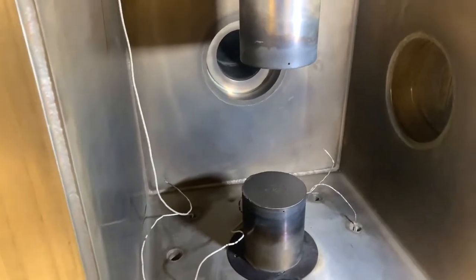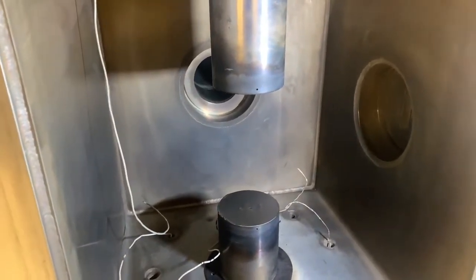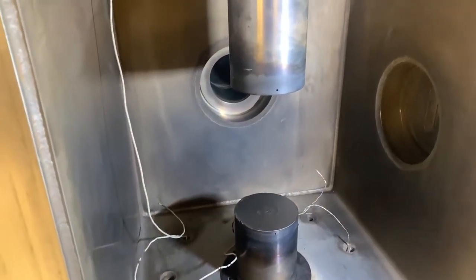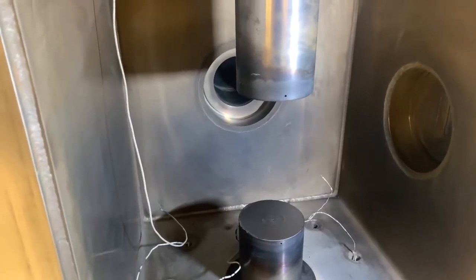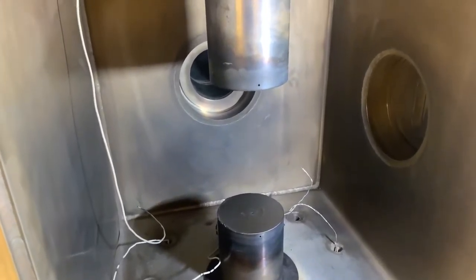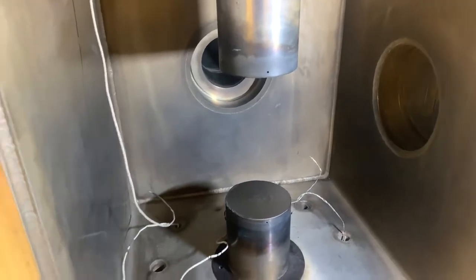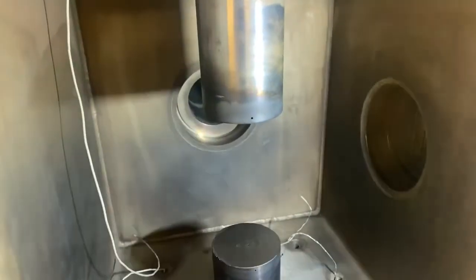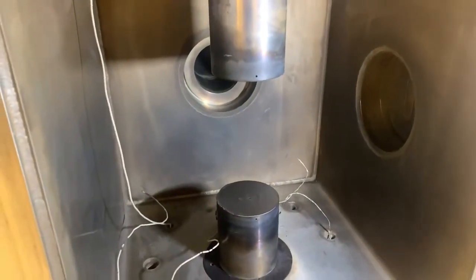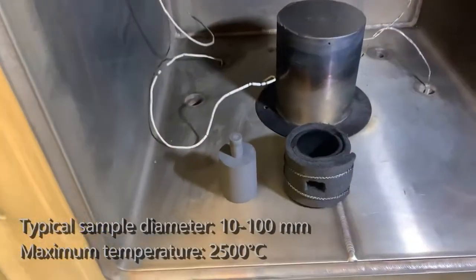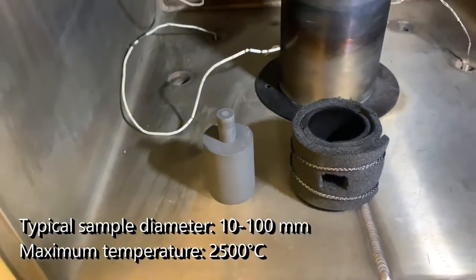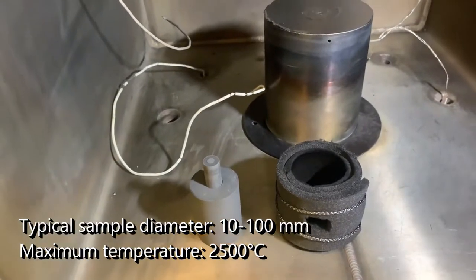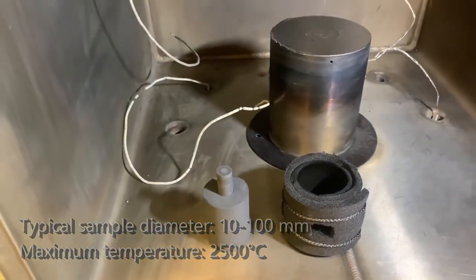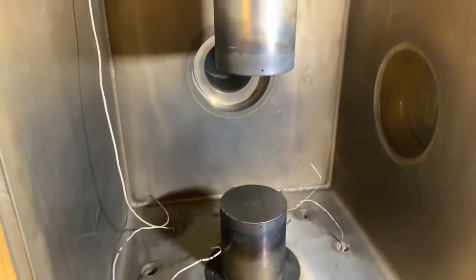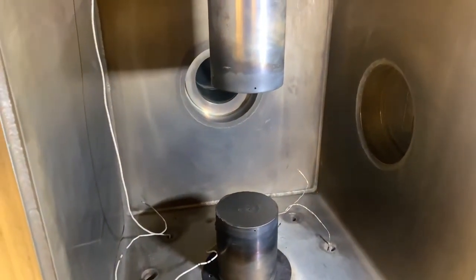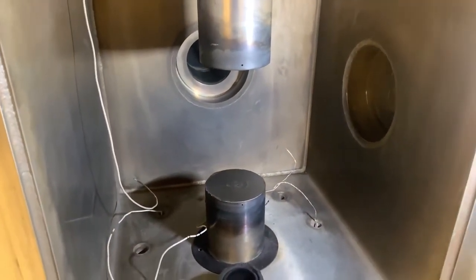You can apply up to about 100 kilonewtons of force. Usually we are in the area of 40 to 60 MPa, and then you compress it first, and then the current that also comes through the rams will get on it, and that will rapidly heat that graphite die system up to about 200 degrees per minute, and yeah, that can get you quick consolidation, and with that you can do testing of your materials.